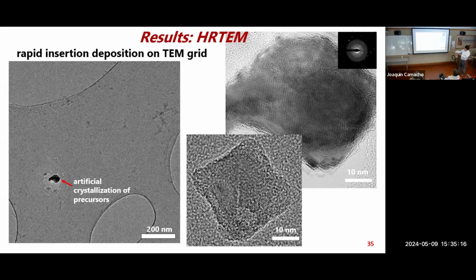But we also see this huge structure here, and zooming in, it's graphite, basically graphite. And even this little pyramid structure here. And it's definitely not forming in the flame. It's probably an artifact of excess hydrocarbons being quenched by the surface and depositing, and maybe even growing as you pull it out. It's like a liquid when it's in the flame, and as soon as you quench it out of the flame, it crystallizes into some structure. So there's a lot of work we have yet to do to separate all these competing processes. But one thing is for sure, these high temperature, high equivalence ratio flames give a unique regime whereby the carbon you can get is graphenic, depending on the conditions, and you can even get these artifacts in there as well.